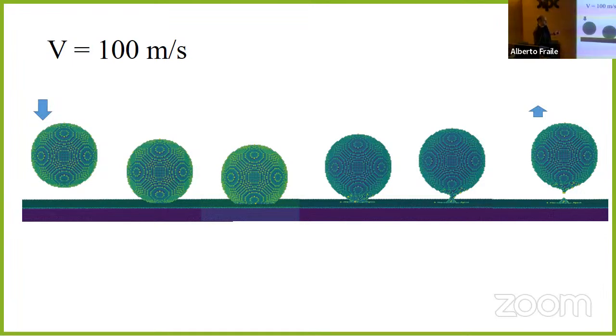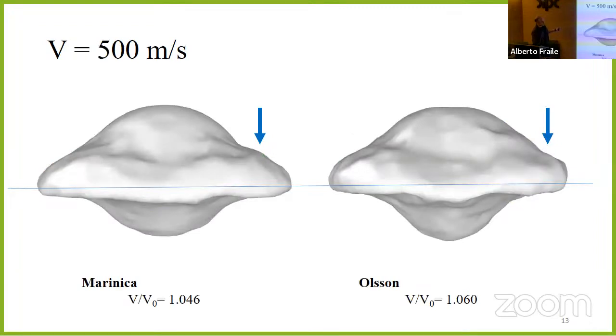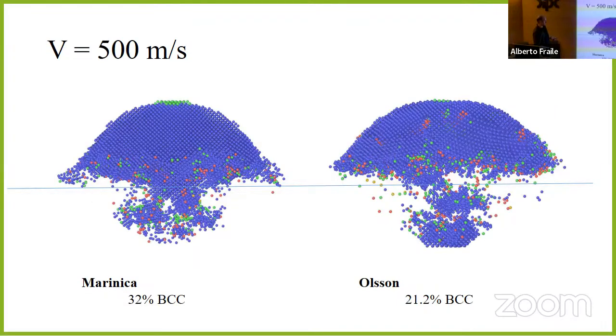And of course, if we do just 100 meters per second, it's not something so exciting. We don't have that kind of excitations and things. In that case, just the impactor touches the surface and then goes up, bounces back. So this is expected, is also observed experimentally, but we didn't study much this very low velocity. When we do 500 meters per second, for example, then the impactor is attached to the surface. So this is the shape that it has. It was spherical before. The volume in the two cases is about the same, volume divided by the volume before the impact. So the shape is the same, but what is not so the same is the amount of atoms still in the BCC phase. So in this case, more atoms are disordered and amorphous after the impact.